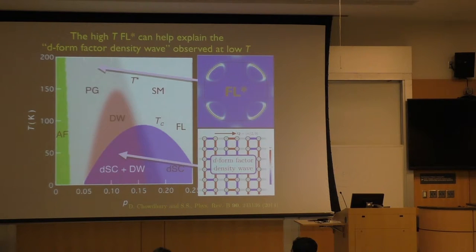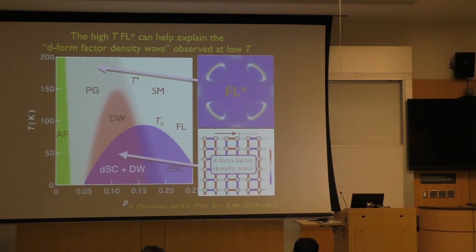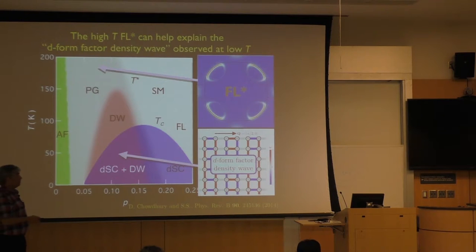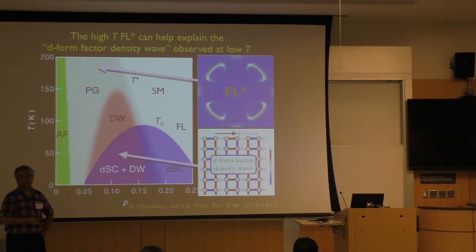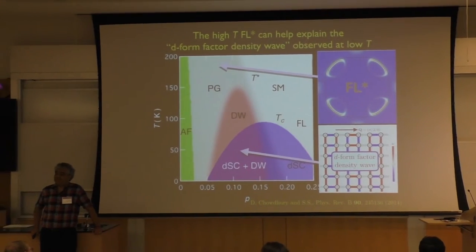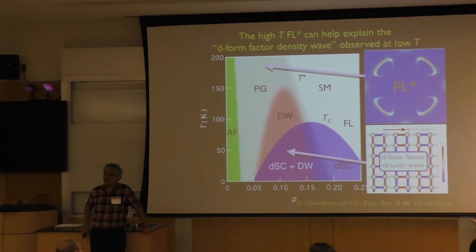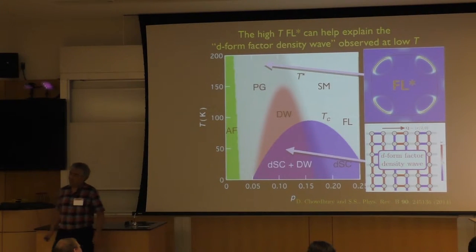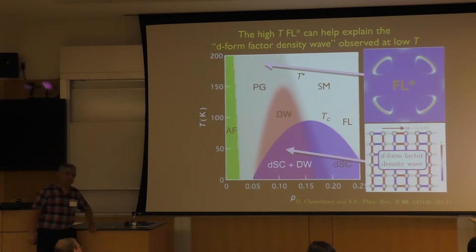As far as my understanding goes, if you look along the nodal direction, it always looks pretty sharp, but only in the antinodal direction it becomes very broad. So I'm talking about the nodal direction — there's anisotropy in momentum space. Correct. This model of FL* has very strong anisotropy in momentum space because there's no quasiparticle data at all on the other side. There are maybe other ways of getting that anisotropy — if you allow for inhomogeneity, you get very strong anisotropy with cold spots.